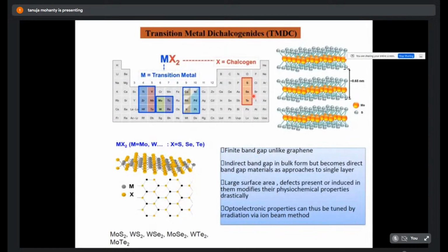But the difference between graphene and this one is that graphene has a zero band gap, whereas whenever you want to use it for solar cells or some applications where you need some band gap, it is not possible. That is compensated in these MX2 materials, which have some band gap which is indirect, but because of the quantum confinement it changes to a direct band gap, suppose 1.2 eV going to 1.9 eV when it goes to 2-dimensional. So the indirect band gap is really not helpful in the bulk form, but it becomes a direct band gap, and the band gap increases when quantum confinement happens. When it approaches the single layer, its large surface area and defects present modify the physicochemical properties. Now, because of these layers, the interlayer bonding is van der Waals, so it is easier to remove. That is the main characteristic.